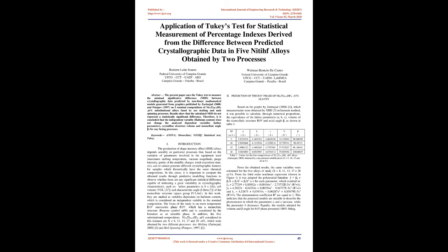In this work, they are studied as variables dependent on hafnium content, which is considered an independent variable in the nominal composition. The focus of the study is on room temperature martensitic phase B19', which has a monoclinic structure, Pearson symbol mP4, and is considered by the literature as an unstable phase.